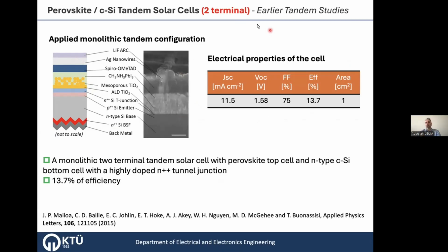This is the example for earlier tandem studies. Again, a 2-terminal example for monolithic tandem structure. It is, I guess, one of the first studies at 2015 as the monolithic structure. You see that they fabricate the perovskite solar cell just stuck on the silicon solar cell. That's why you see it as a standalone solar cell. In this case, the recombination junction is a heavily doped N+ layer, which makes the barrier and makes the tunneling. This layer here acts like a recombination junction and makes a two-terminal monolithic tandem configuration with an efficiency of 13.7%.